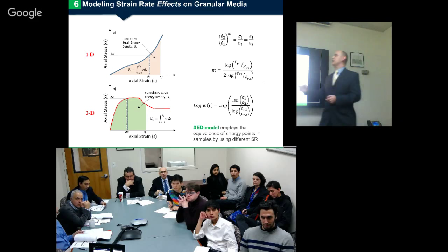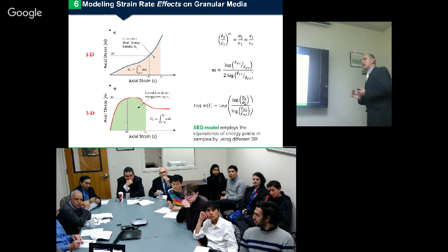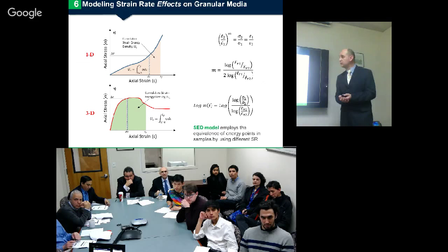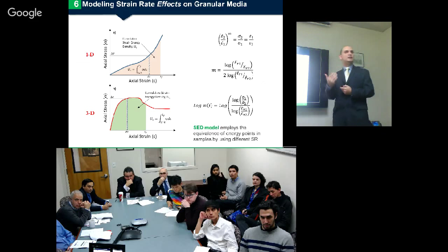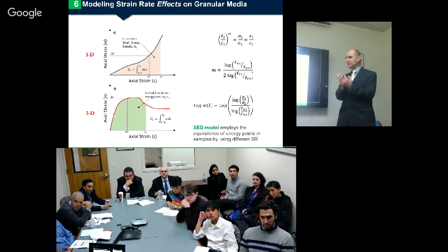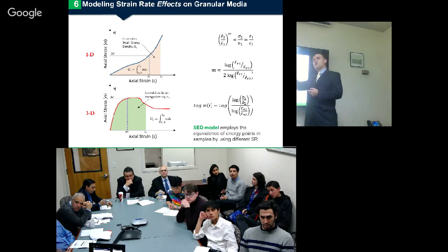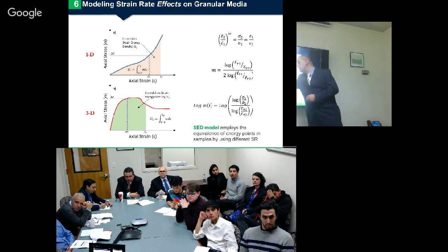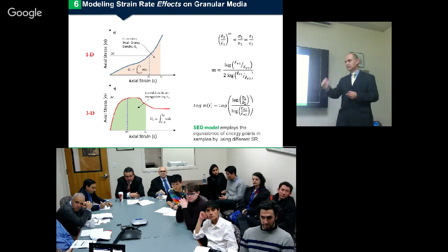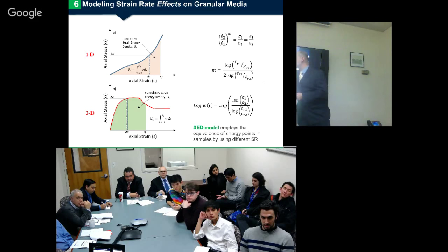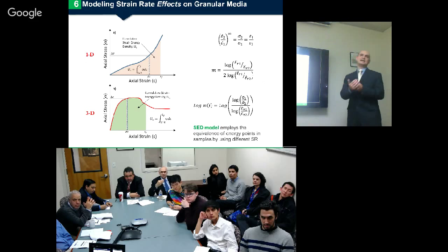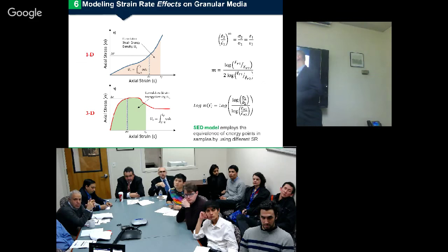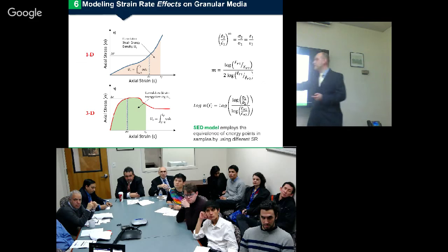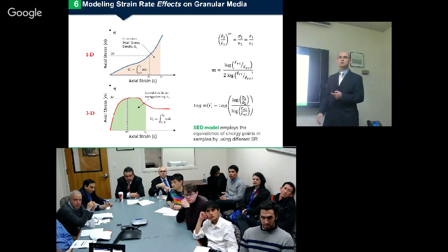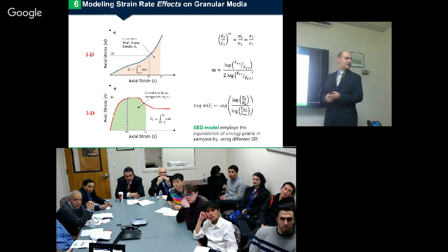Basically, what we have here is, in the upper left side of the screen, in one-dimensional conditions, as we saw earlier, the load is increased, the material is being affected, but there is never a failure of the material as a whole. Whereas for these, we see the peak deviatoric stress. So the area under this curve can be defined as a strain energy density, and the addition of the small slices for each one will be, in this case, U sub U, which is the cumulative strain energy density.